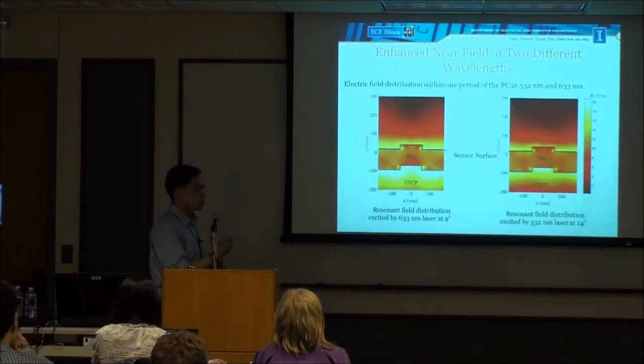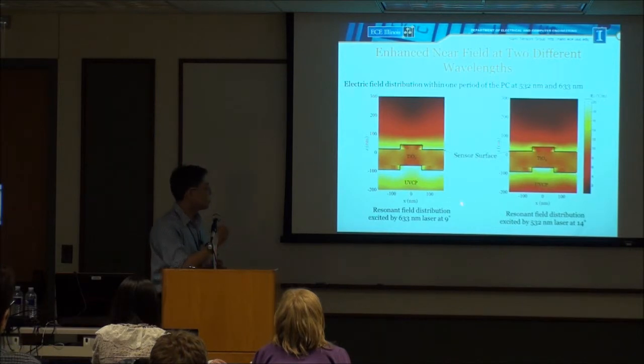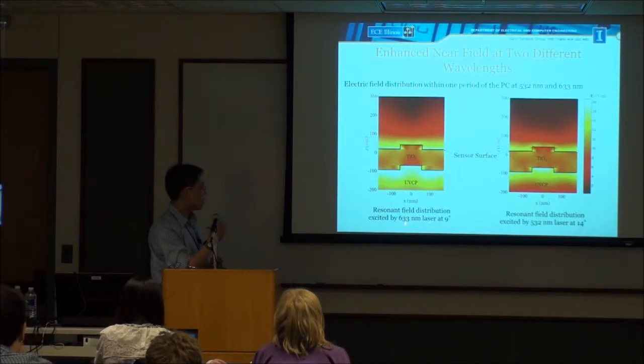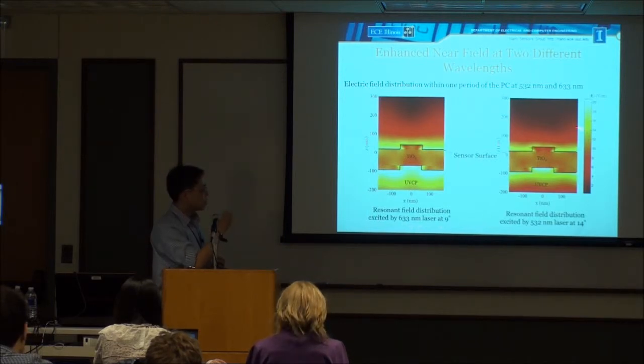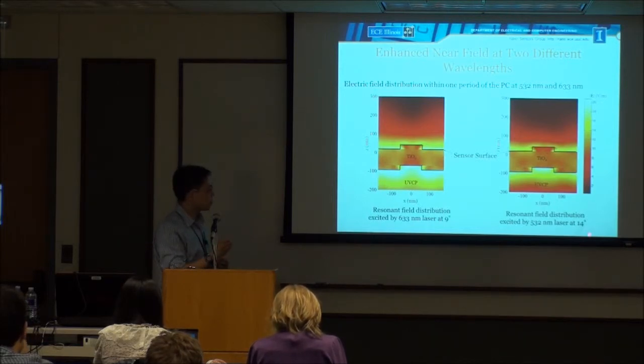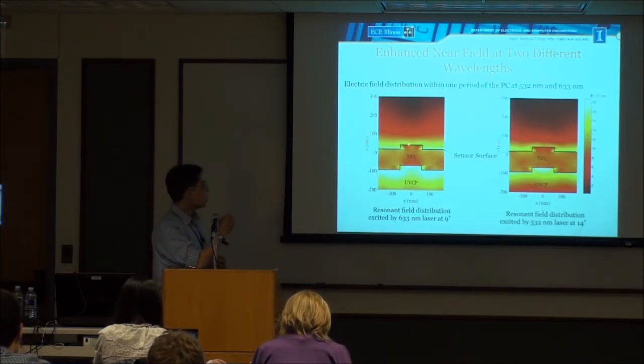So from simulation, you can show the enhancement for both wavelengths. The left figure shows the local field, the resonance field distribution, which is coupled with the 633 nanometer laser at 9 degrees. This figure shows the field distribution excited by the green laser at 14 degrees. As you can see, both of them have enhancement on the sensor surface.